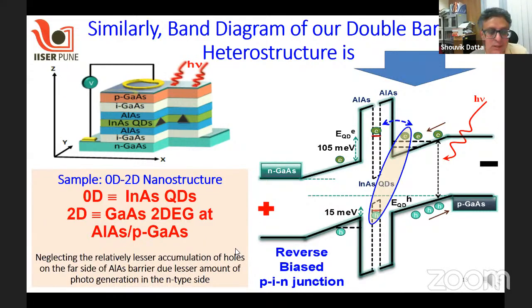In this structure, we call this a 0D-2D structure, because 0D corresponds to the indium arsenide quantum dots and 2D corresponds to the gallium arsenide 2D layer at the junction of aluminum arsenide and gallium arsenide, where photogenerated charge carriers accumulate and create a two-dimensional electron gas.